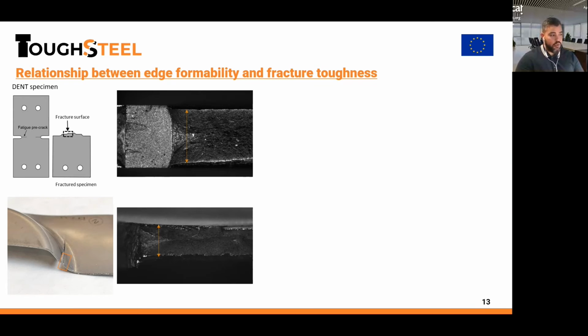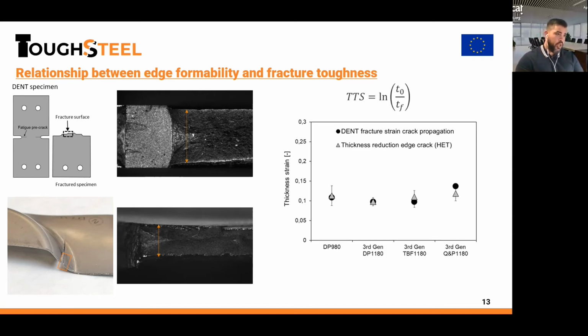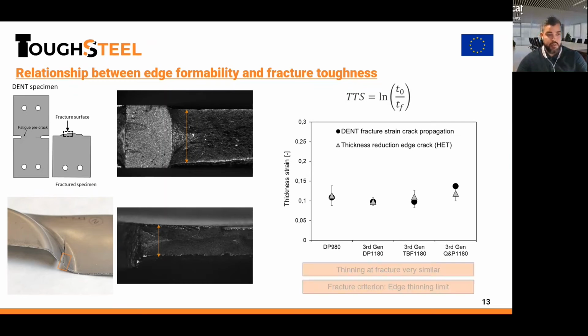Also, if we measure the thinning ahead of the crack tip in these two experimental setups, what we found is that measuring this true thickness strain, which is measured by the reduction of thickness at the crack tip, when we compare these strain values in the pre-cracked specimens for fracture toughness testing, and measure similarly the thinning near the edge crack in the hole expansion test, surprisingly or not, because coincidentally, these fracture strains or this edge thinning were very similar for both of them.